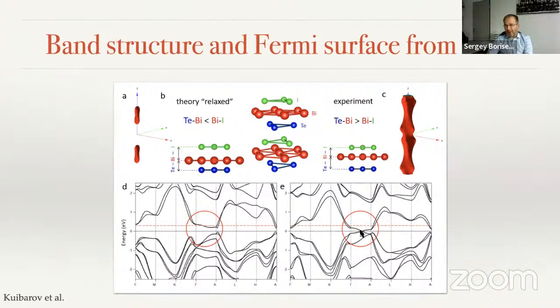And actually, the Fermi surfaces from ARPES experiments, where the Fermi level is drawn according to the common wisdom, what is more or less generally accepted by the ARPES community until our study. This is the 3-dimensional Fermi surface. And this is the Fermi surface which is suggested by our studies. So the difference is dramatic, but interestingly, at least we didn't find Hall effect measurements in the literature which would show that the charge carrier concentration is significant in this. So let's have a look at what ARPES shows.